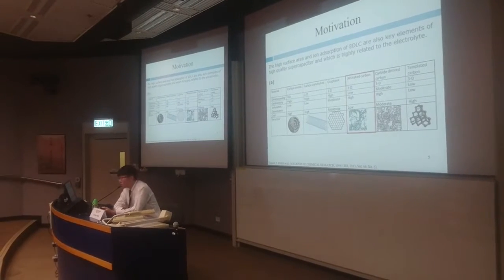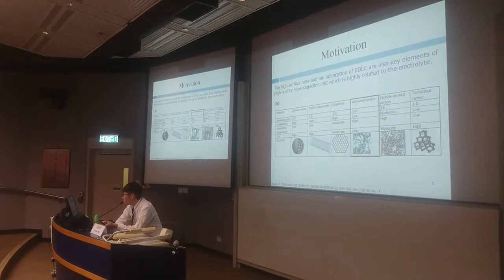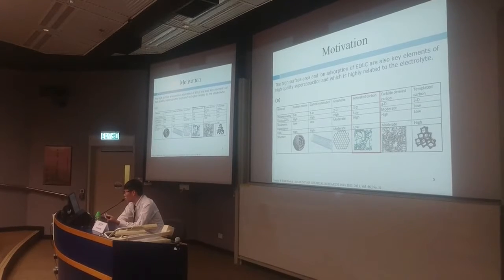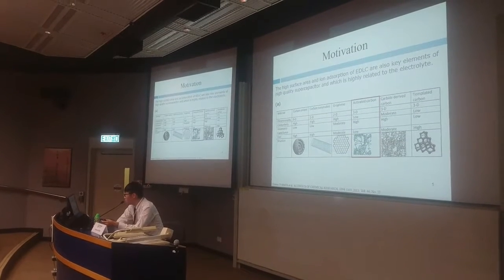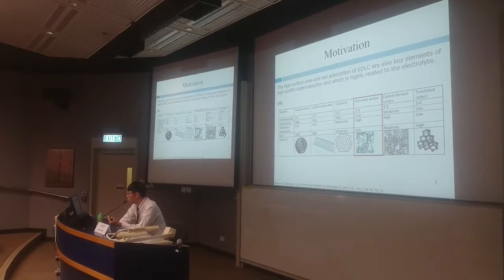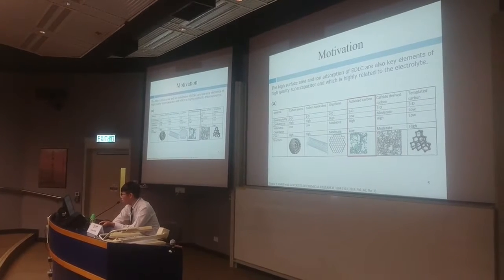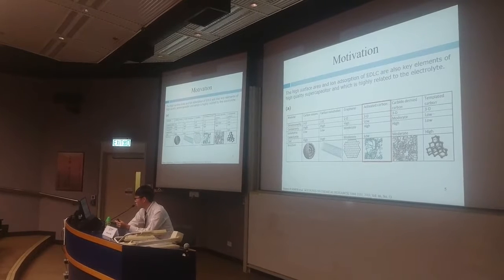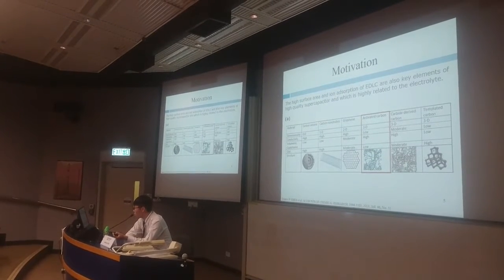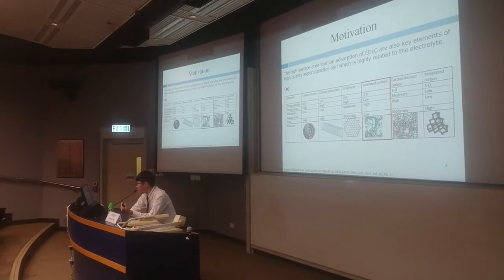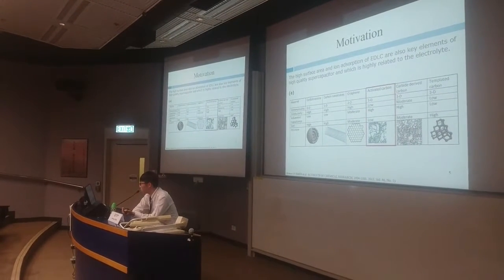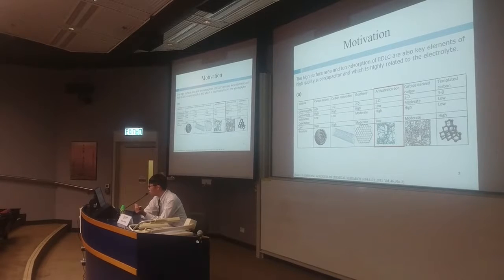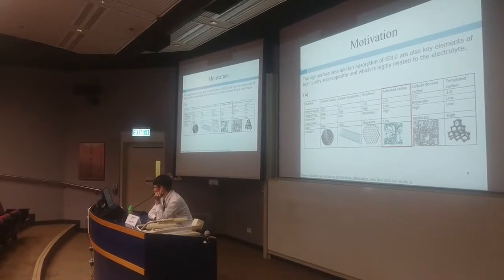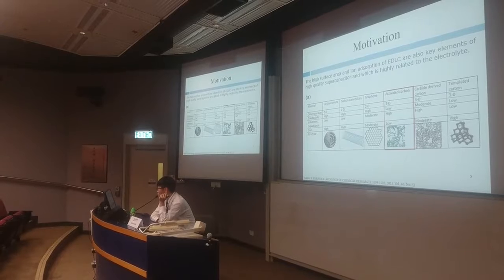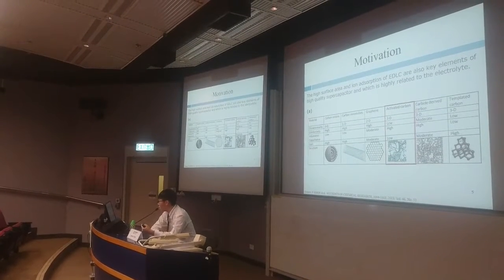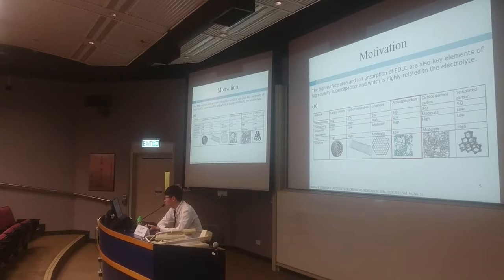Here shows 6 typical types of carbon electrodes for the EDLC device. So in our previous work, we have used graphene as electrodes and different concentrations of organic solution as electrolytes to investigate the diffusion number and the capacitance. Compared with the graphene electrode, the activated carbon electrodes offer much higher surface area and volumetric capacitance.